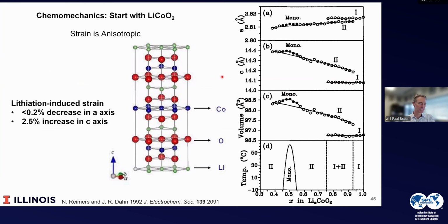And so this goes back to this discussion about chemomechanics. If I take lithium cobalt oxide, as I cycle it, there is strain. So the A-axis decreases as I pull out the lithium. So that's moving to the left is removing the lithium. The A-axis decreases. The C-axis, as I remove the lithium, it expands. And so this crystal is trying to change shape. And when it changes shape, it, of course, builds up a lot of interfacial stress.